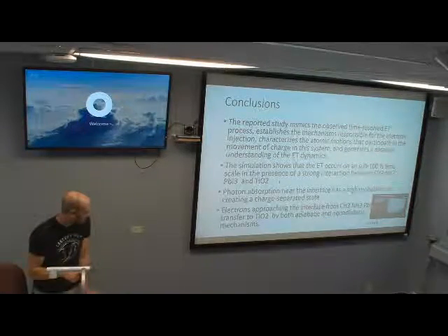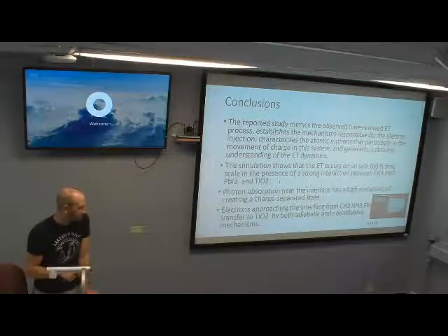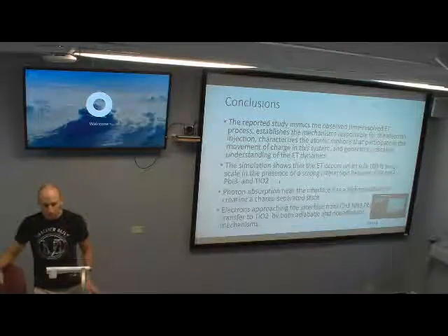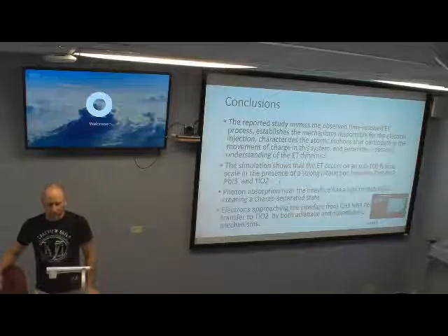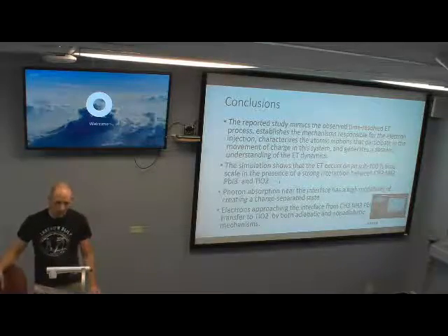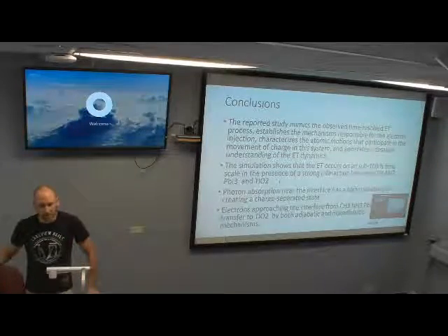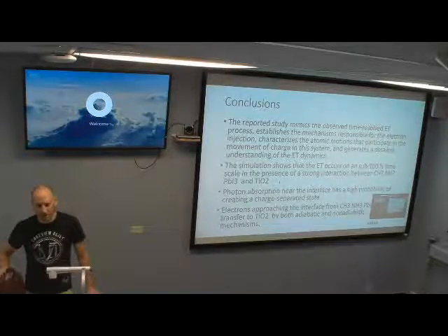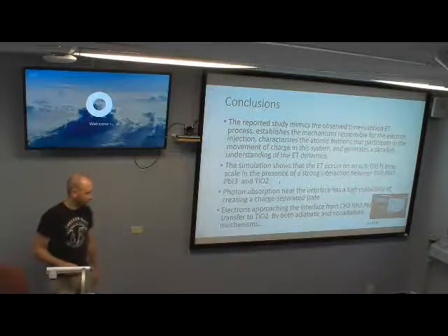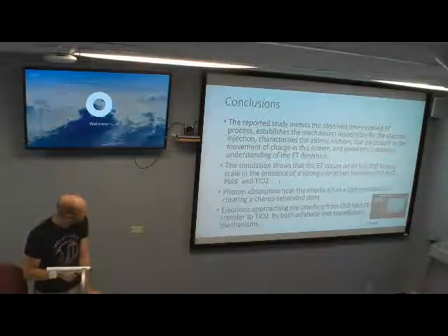They found that it works on a sub-100 femtosecond timescale if you do the excitation near the interface, again with very high probability. This is what was seen also in experiments, right? Yes, the ones that were able to measure down to that timescale usually found 100 femtoseconds or less. In experiments they probably cannot tell exactly how long it takes, but they can say not longer than that. The longest one was less than 2 picoseconds, and I imagine that's just because they don't have the resolution to go down farther than that.